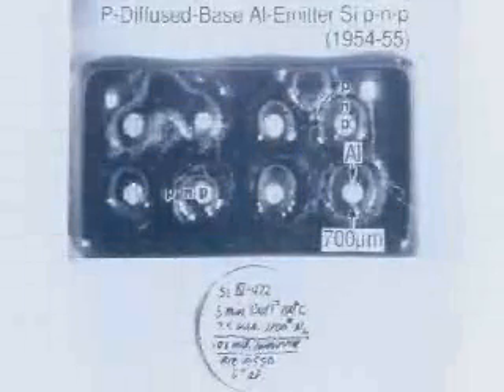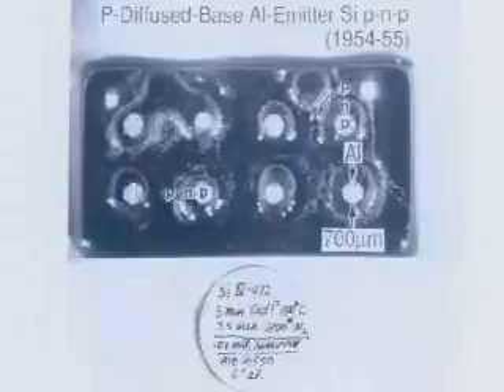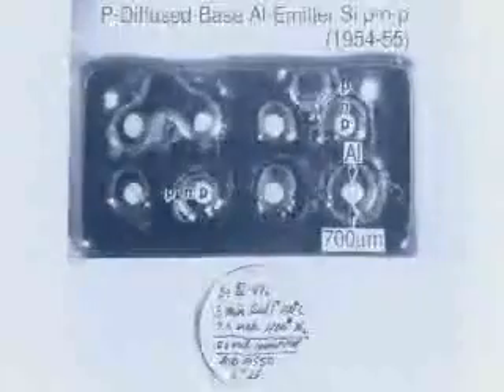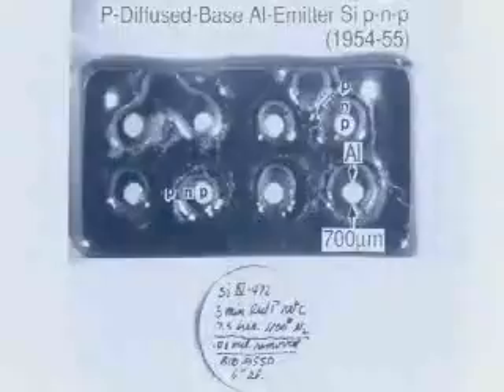And here, at Christmas 1954, here's what we already had made. This is a P-type piece of silicon. We have diffused into the top some phosphorus. That was not simple to do, and I had this in a pill box, and here was some of my writing that said what we did: 5 minutes, red phosphorus, 700, 7.5 hours, 1100 in nitrogen, drive in, 1/100 of a mil removed. Then here's my recipe for how I evaporated the aluminum. But at any rate, there's an N-type layer on top of this crystal, and then we have evaporated this P-type aluminum there, and we have made a PNP.